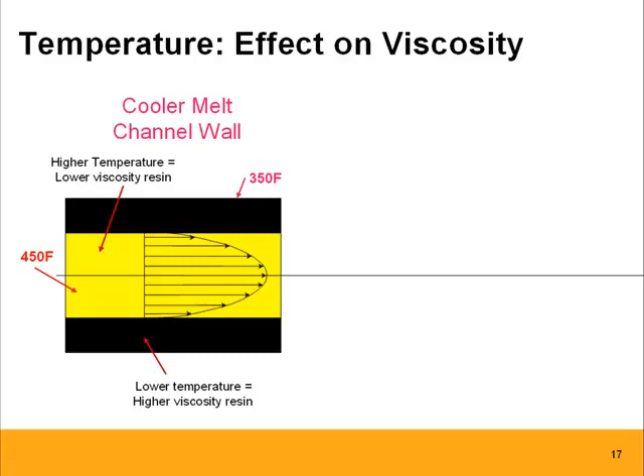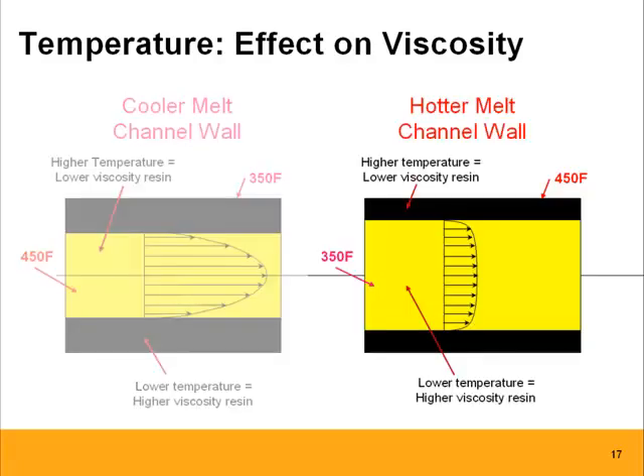So a better situation would be if we actually increase the melt channel temperature, therefore changing the viscosity of the resin, lowering it, and pushing from the inside the same resin at a lower temperature. And by lowering the temperature, of course, we're changing the viscosity and making it a tougher material to push, and that actually helps for color change. That's one way of optimizing color change.